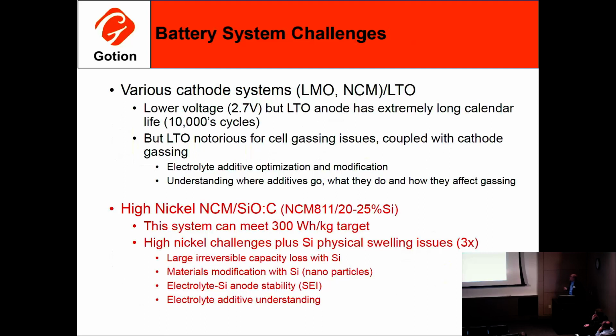Last current system is the NCM silicon system. And so this is, like I said, the short-term goal. This is going to get us and people that use this cell to the 300 watt-hour per kilogram target. And typically what it's probably going to be is an NCM 811 to get the high capacity on the cathode. And it's going to be a silicon anode with somewhere between 20 to 25% silicon, and the rest will be graphite. But another complication, silicon loves to swell up when you charge the battery and put the lithium into it. So it's a physical swelling, not a gas swelling. And so again, that's another challenge.